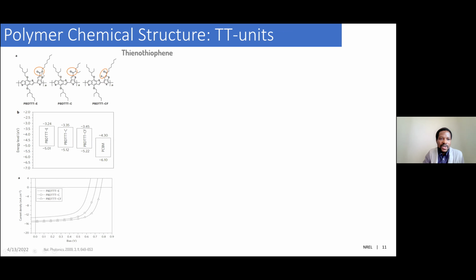So here we have a kind of, you reduce your oxygen, and you get a ketone type of TT substituted polymer. And then when you fluorinate it, you also improve the molecular dynamics. So in that sense, they try to play with the VOC in the system when you combine it with PCBM. As you can see here, they've been able to achieve that by just playing with the substitution on the side chain of the TT. And we look at that also in detail.